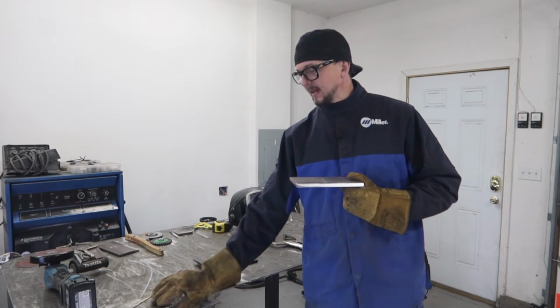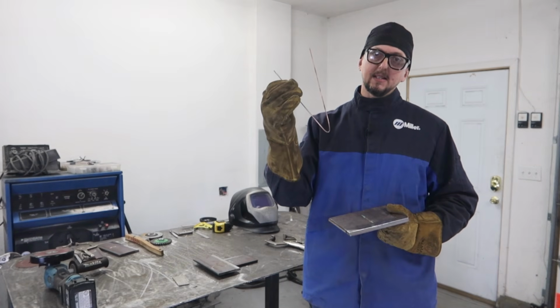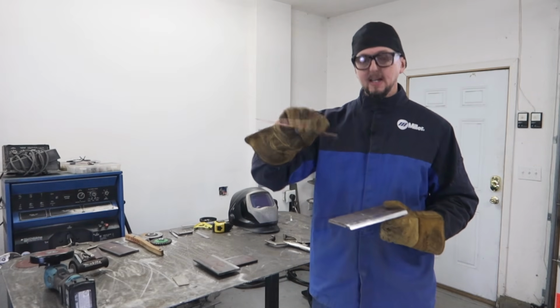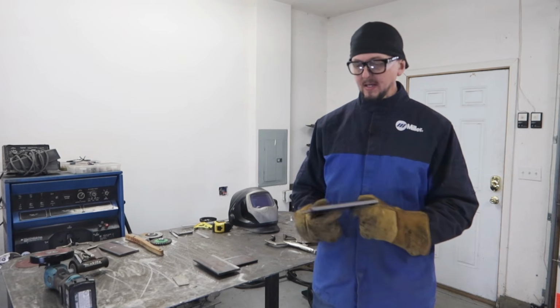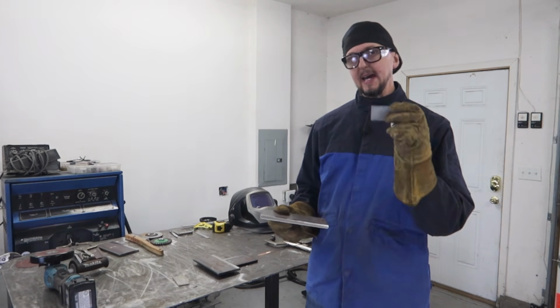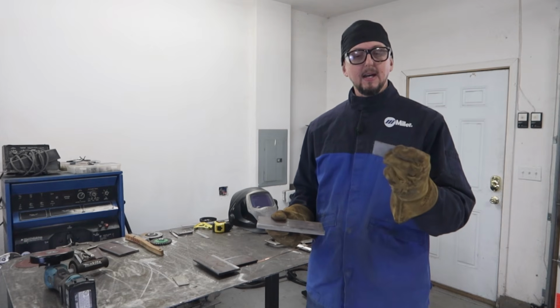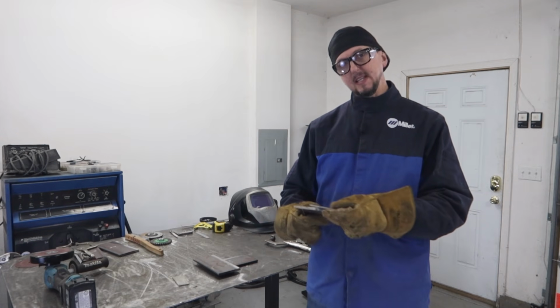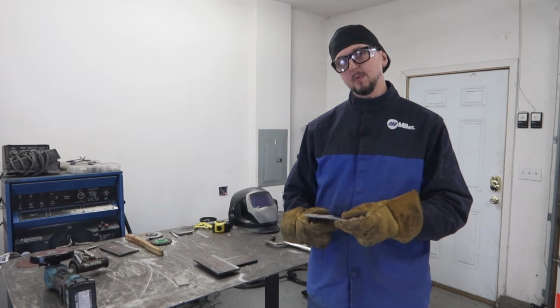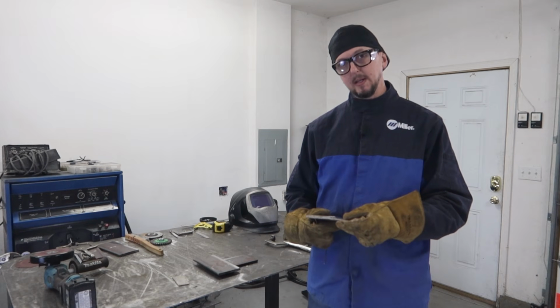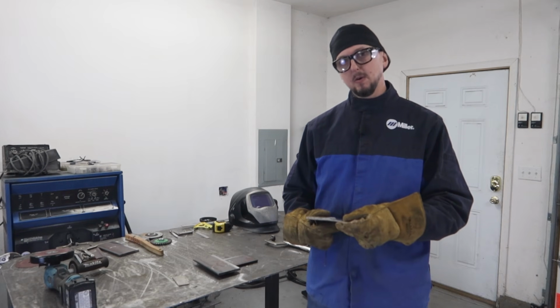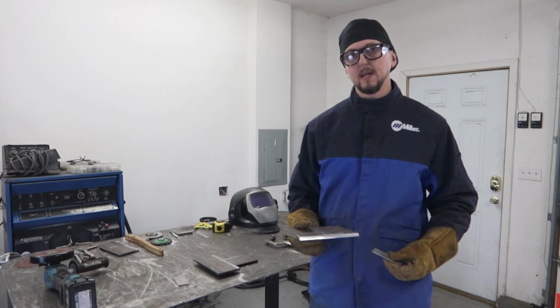So I have some filler metal that I've cut to size just in this little V to be able to space that root opening. And then I also have some little tabs, just some scrap pieces to fit up to the ends, which will help keep that root from closing up as we weld it, and just give us a nice open root all the way through the joint.